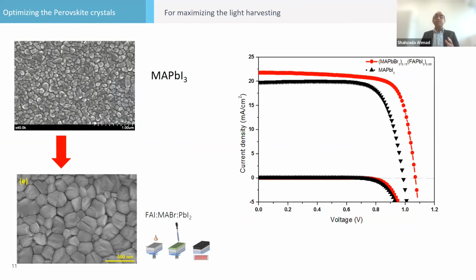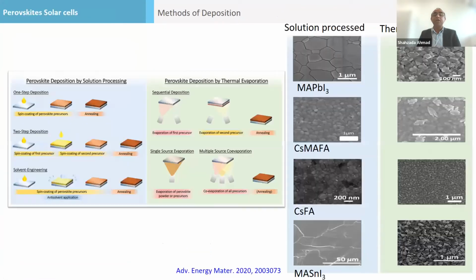When we started to work, just to give you a flavor, the crystals were very small, with methylammonium lead iodide. Now the crystals are larger. Sometimes we have even more than 1 micron or 2 micron crystals. So if we maximize the crystal size, we reduce the defects. If we reduce the defects, we can harvest more energy, and we get lesser recombination and higher voltage.